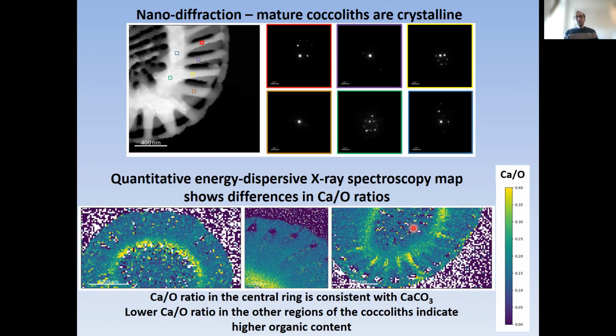To check for that, we did some other measurements on mature coccoliths. One of them was nanodiffraction, and this is just to confirm that the coccoliths are single crystalline calcite, and this is really what we see. It's clear, it is a diffraction pattern taken from a different region in here, and that follows pretty much what is known in the literature. Each one is a single crystal of calcite, so nothing much to see there.